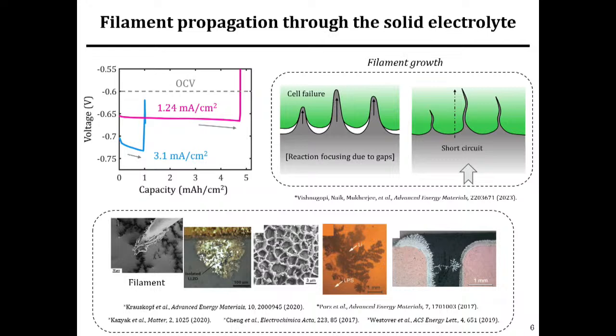This is again from the recent work we published, showing that as you increase the plating current, the reaction and mechanical heterogeneity exacerbates at these interfaces, which can eventually result in the growth of filaments through the solid electrolyte separator and resulting short circuit. We delineated a few mechanisms, such as contact loss and mechanical extrusion of lithium into the solid electrolyte, that are responsible for such failure mechanisms.